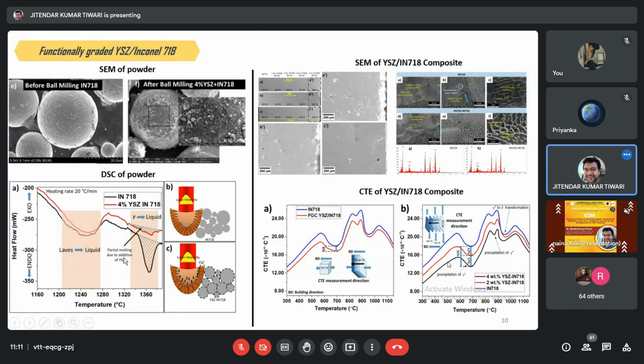So basically, this is representing the DSC curve, that is differential scanning calorimetry. The idea of performing this test is to understand the liquefaction behavior of the parent powder and the mixed powder. When we mixed YSZ, as you can see here, these white color particles are the YSZ particles, and they are adhered on the surface. They will cover the powder particle, and the heat coming from the laser will not be properly transferred to the inside, to the parent material Inconel 718. So obviously the liquefaction behavior will get affected, and there will be partial melting of the metal powder.